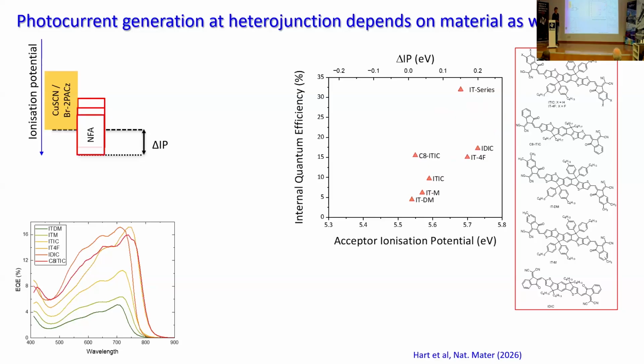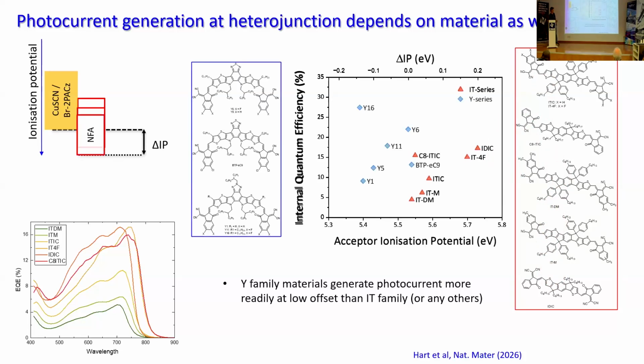But the interesting thing here was when we changed the material family. These are the ITIC material family, but when we go to a Y material family, including Y6, which is one of the best performing materials, and other analogs, we see the same behavior, but it kicks off earlier. So it looks as though the Y family is able to generate photocurrent at a smaller offset than the ITIC family. That's something interesting that we wanted to understand.